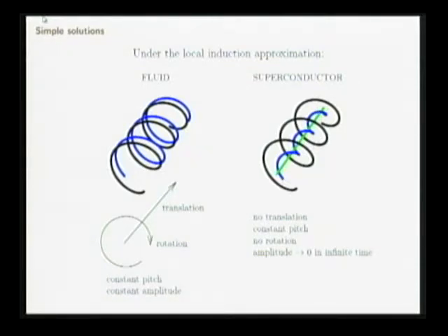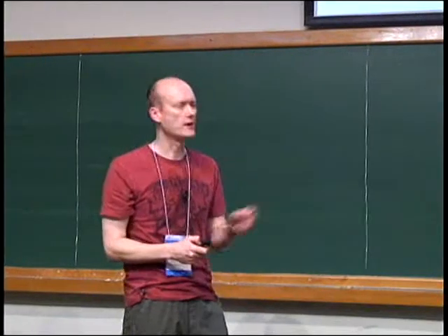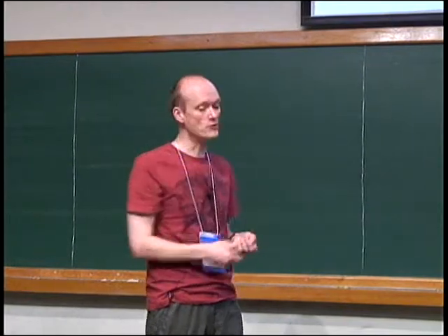And so the helix basically straightens into a line, but this time it takes infinite time, because as it straightens, the curvature goes down, not up. So superconducting vortices act a little bit like they've got a line tension. If you had a filament with tension, it would want to straighten, and the force would be proportional to the curvature. The more curve, the more force. So that's a way to have a bit of intuition about how a superconducting line vortex is going to behave. It wants to reduce its length.